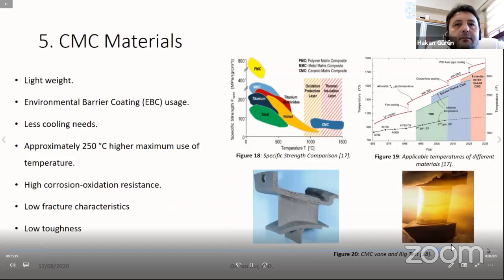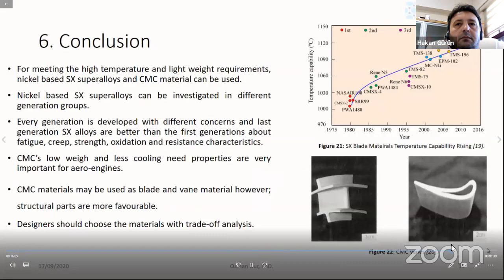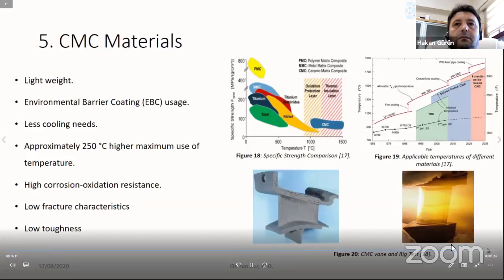In these materials, environmental barrier coating is used, which is an advanced ceramic system used for different purposes. CMC materials give a 250 degrees Celsius advantage when compared with single crystals. However, it has low toughness. Because of that, stationary parts are more suitable for CMC usage. As you see in the figure, CMC materials' specific strength is lower than the metals. Another picture shows the temperature capacity of the CMC materials, which is much higher than metallic alloys.